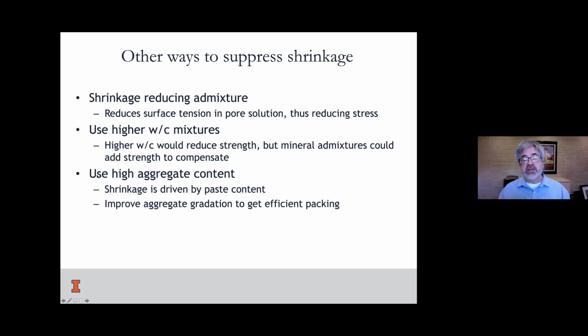The other thing is just good concrete technology. Use high aggregate content. Remember, this whole problem is in the paste. It's in that water and cement component of the mix design. That's where it all is. How can we squeeze the pie and get that to be smaller and smaller? Well, one way is to find ways to increase aggregate content.